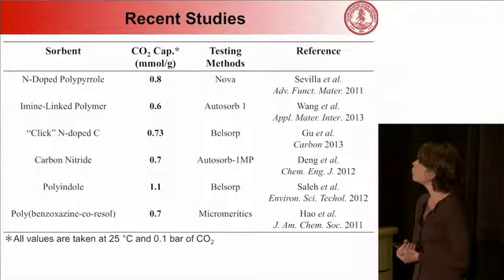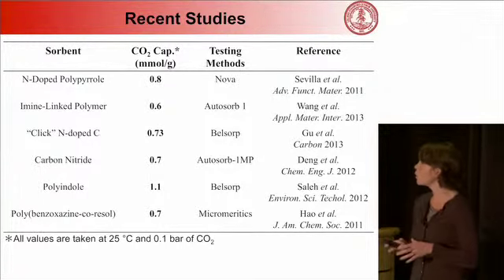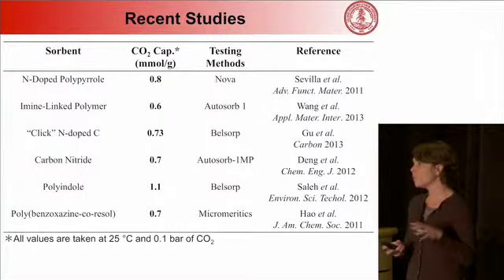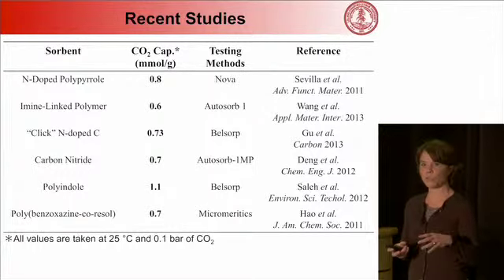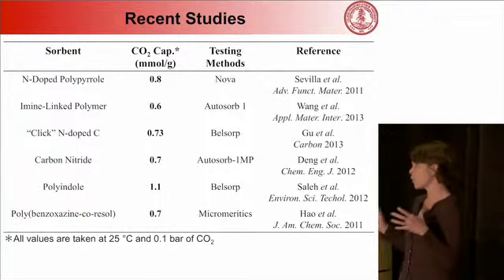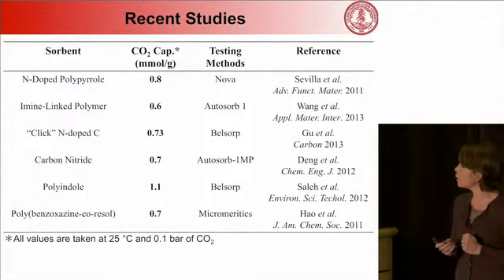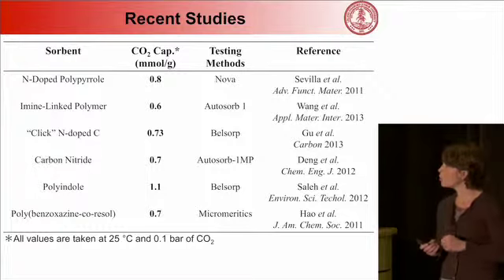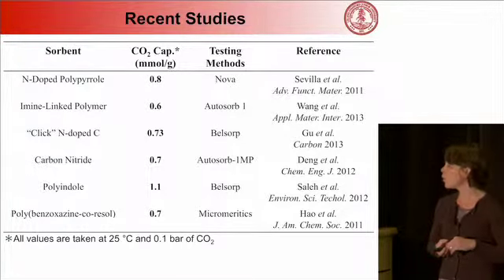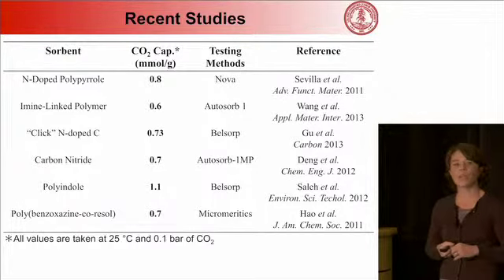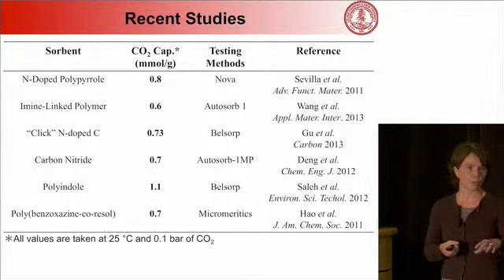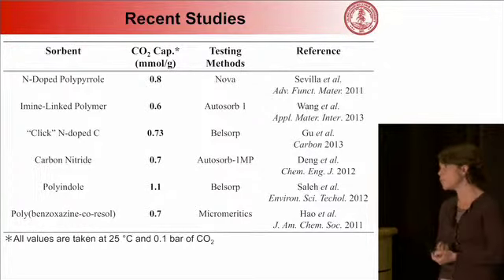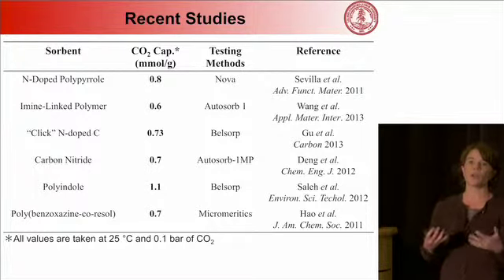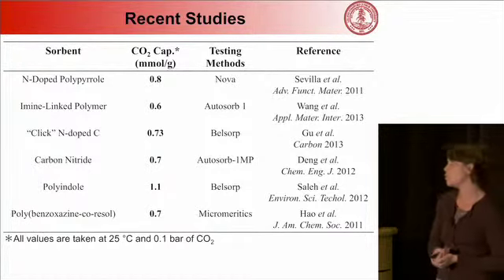But we have essentially this polymer with cross-linking, and that cross-linking helps to dictate the porosity and also the pore size distribution of the material, which is somewhat tunable, which was kind of the goal, which I'll talk about a little bit later. In addition, there are nitrogen groups comprising this basic substrate. And we're hoping that those nitrogen groups can enhance the uptake of CO2. Although we're eventually going to functionalize the surface with zinc, we think that we could actually have some enhancement in terms of CO2 uptake beyond the zinc with the fact that we have nitrogen functionality in the material.